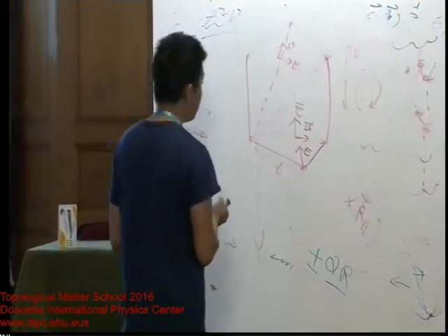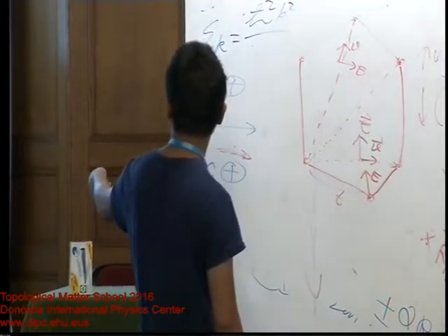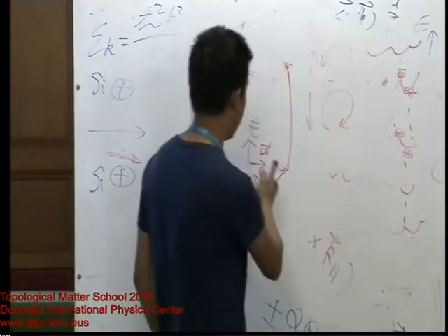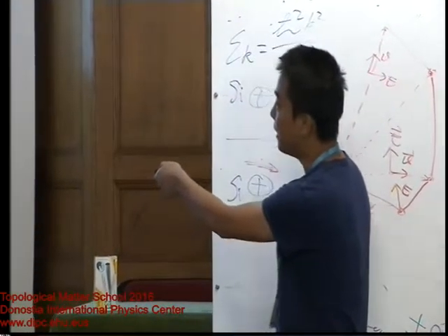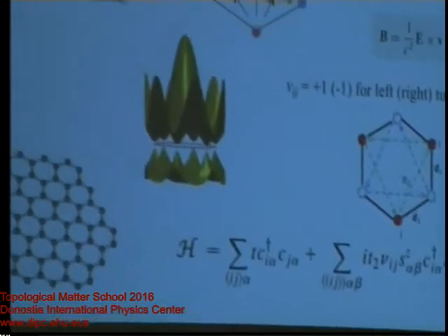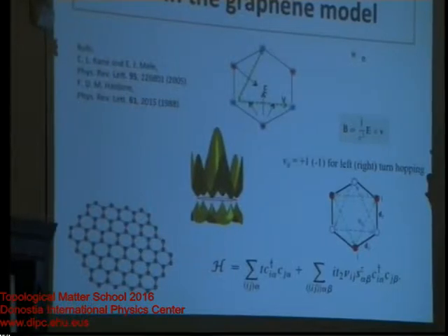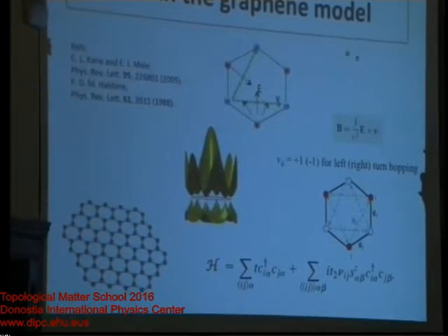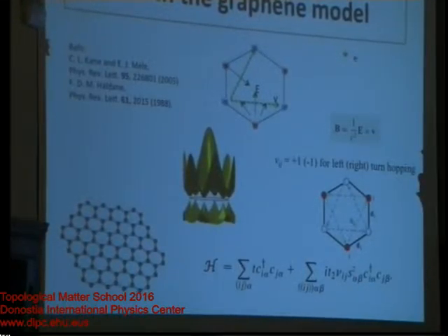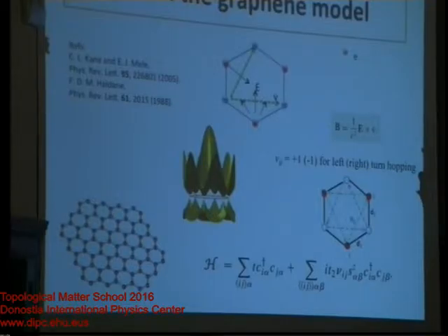sigma_z times h-bar over 2. And then, of these two terms, the most important is this nu_ij and S_z term. This spin selective hopping, actually just means spin selective hopping. And it will generate a gap at the Dirac point. Originally in graphene, we know the Dirac point is a semi-metal. Now formally it becomes an insulator. And then, repeating again, how strong can this term be? And here we see its source is from the electric field of this atom.